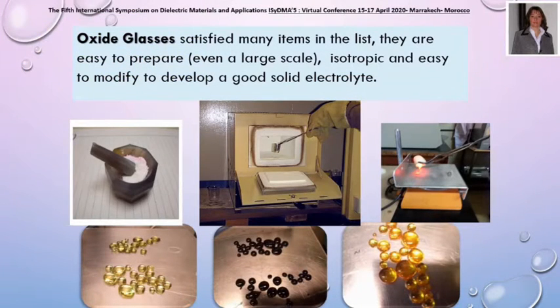Then we bet for glassy materials, because they have almost every property listed before, and added to that, they are easy to prepare, only mix and bake. They are isotropic and easy to modify also. Quenching method is the most popular to obtain glasses in a large industrial scale, and it has a good reproducibility. As you can see in this picture, glasses formed with many different oxides are obtained just finding the correct cooling rate.